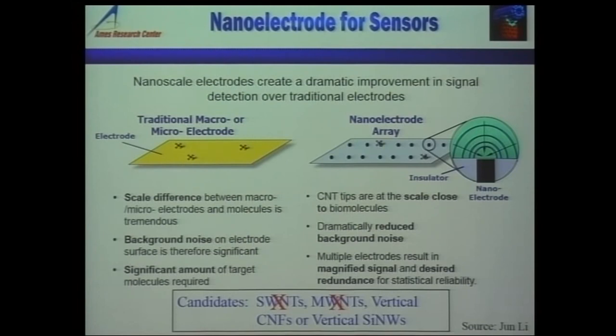Carbon nanofibers, silicon nanowires, or zinc oxide nanowires — if you can grow them nice and vertical, you have one electrode and then an identical nano electrode at a chosen distance apart. For a 50-nanometer electrode, the radial diffusion layer in electrochemistry requires that the neighboring electrode should be at least about one and a half microns apart, so that the two act like individual electrodes. If they are any closer together, the diffusion layers overlap. When all diffusion layers merge, they behave like a micro electrode — and that is the biggest issue.